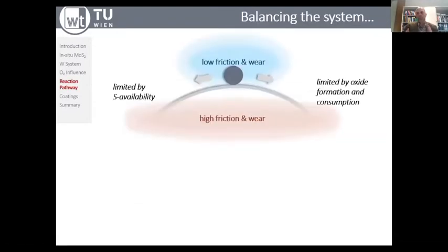So coming to an intermediate summary, it seems like we need a balancing of the system. There is a kind of equilibrium that is governed by two things. First, of course, we need a sulfur source. We have a limitation by the sulfur availability that comes from the additives in the lubricant. On the other hand, we have a limitation by the oxide formation and consumption, because when you do the sliding test, of course, you are mechanically removing the tribofilm that is forming, and you also create it again in the contact and you replenish the contact again.